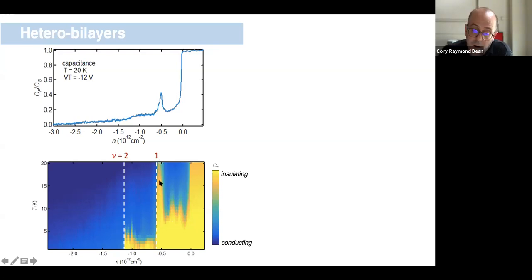But if we underdope, so if we go to lower doping, below some threshold temperature, actually the whole system appears to become insulating, becomes incompressible by capacitive spectroscopy. And if we overdope, it again is the case that the whole system, as long as we're less than filling fraction 2, is insulating. And that crossover appears to happen at a fairly well-defined transition temperature. But it happens at a different transition temperature for filling between 1 and 2 versus filling less than 1.